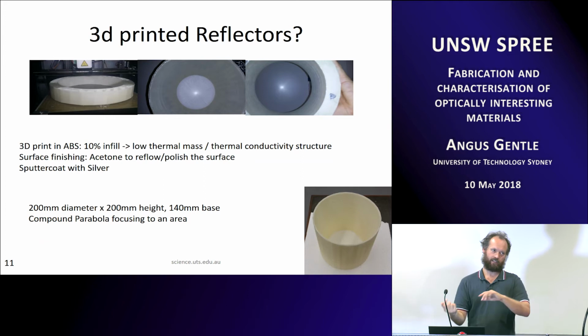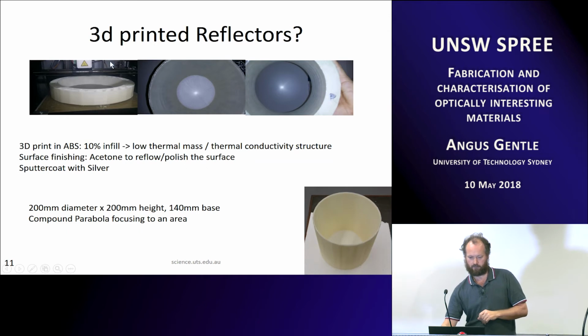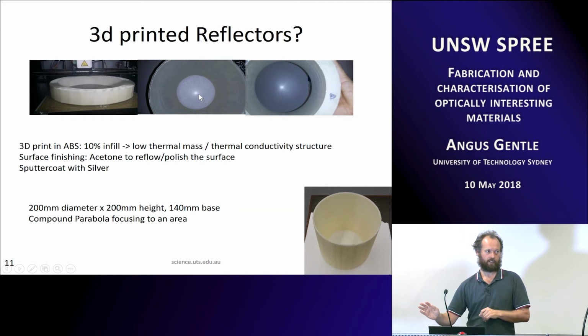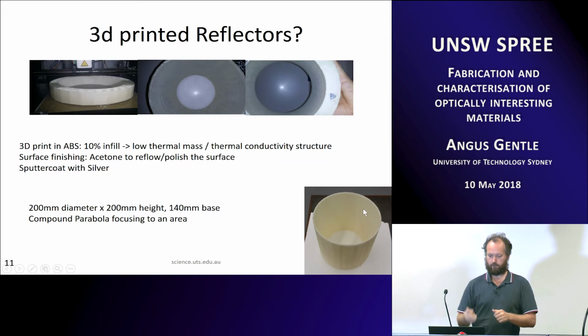After that, we put it in the vacuum chamber and then sputter it with silver, so you get a really nice reflector. These photos here, where you can see it's reflecting down and focusing down to a point, that's before the silver coating. So this is just the plastic that's had acetone put on it, and you can already see that it's focusing down quite nicely because of the high angles that are involved there. This one here was like 200 by 200, 140 mil base on it. And using that, we can put that outside and then get very cold temperatures.